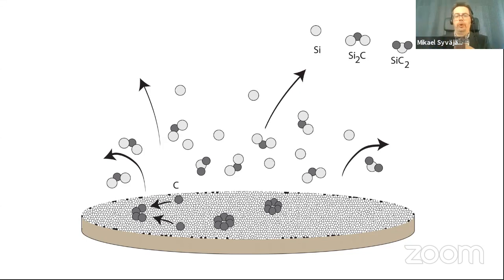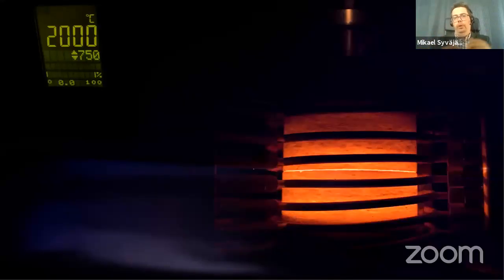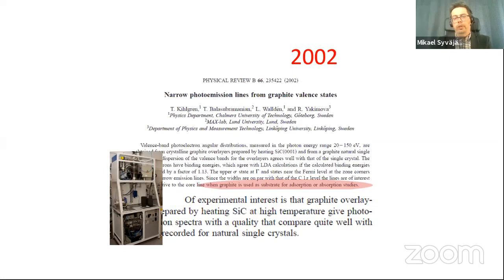bad for the growth. But that's how we came into an avenue of making thin graphitic layers on silicon carbide using this process. So that was done in year 2000, 2001. We started to explore thin graphitic layers on silicon carbide. And it was by curiosity we started to look at this process, because graphite can be interesting. And then we use high temperature to initiate this process for making thin graphitic layers. So there were some results, in collaboration with Chalmers, which show that these thin graphitic layers have very high quality. So it's almost like natural graphite.